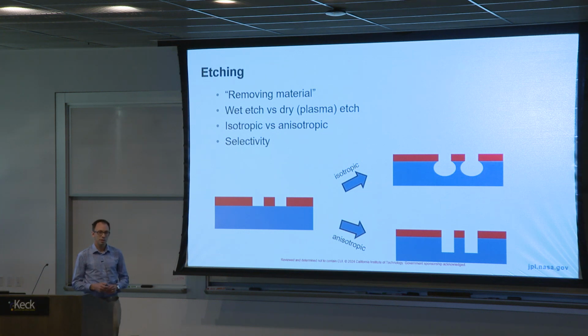The concept of selectivity is pretty important when we're talking about etching. Selectivity is essentially a number, let's say 10, and it tells you how much faster you're etching, in this case, the blue material that you want to etch, than you're etching the red material that's working as your mask. So if I have a selectivity of 10, you etch the blue material 10 times faster than you're etching the red one. It might seem like a minor detail, but this is very important because it tells you how thick your mask needs to be. If your metasurface design calls for an etch depth, a pillar height, of let's say 10 micron, and you have a selectivity of 10, you know that you need at least a micron of red masking material.